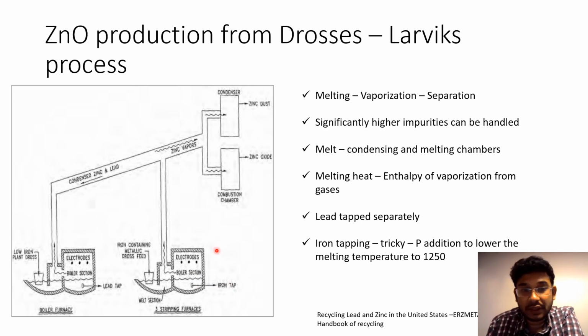And other than that, it is quite literally the same as, let's say, the Muffle furnace in terms of chemistry. But even here, I have to say that if you throw in a waste with aluminum, it's not so easy to handle, because you have formation of really complex ferro-aluminum alloy, and that's not going to melt, that's going to go everywhere, and that's not going to be easy to be processed in the Larvik's furnace.